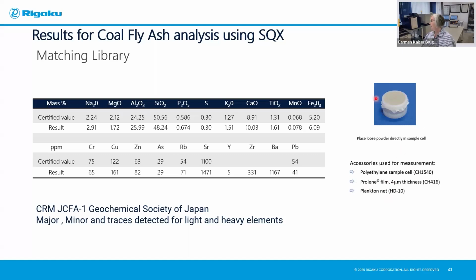And of course, we can create the analysis that we get as a matching library. So it's like a fingerprinting of our materials. If we set it up as a matching library, then we can measure the sample using the matching library, and these are the results that we can get. You can see the certified values on the top for the major and minor elements, and then at the bottom, the trace elements in ppm. And you can see that the actual results obtained are very close to the certified values using semi-quantitative matching library. So very useful.